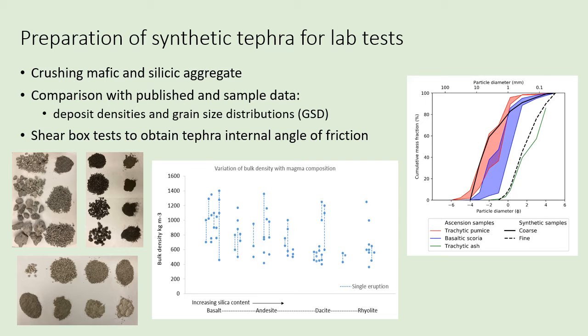However, before I can start the sliding tests, I needed to create synthetic tephra, as it's not been possible to obtain large enough samples from Ascension. So I've been crushing and sieving commercially available mafic and silicic aggregates. To ensure the test tephra is representative of real-world deposits, I compiled published data on bulk deposit densities for a range of eruption sizes and magma compositions. And as you can see from the centre plot, there's a wide range within single eruptions, between eruptions of similar compositions, and across different compositions, but no clear overall trend. So I'll be ensuring the deposit densities for the sliding tests fall within this range of values.